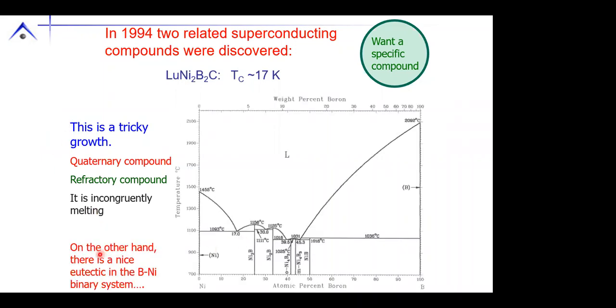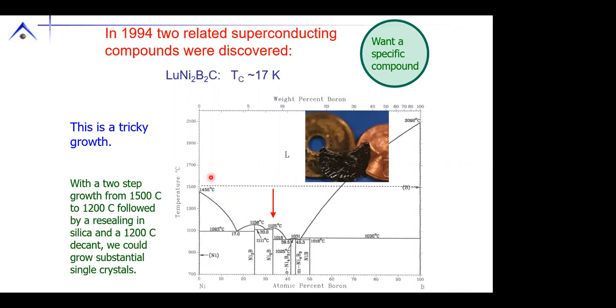So what was nice is nickel and boron have high melting points by themselves, but have this cascade of eutectic valleys. So this offers a region where we might be able to grow samples. Indeed, we developed a 2-step process where we would cool from 1500 to around 1200, crash to room temperature, seal in silica, reheat to 1200, and then be able to decant and get beautiful single crystals of lutetium nickel 2 boron 2 carbon.